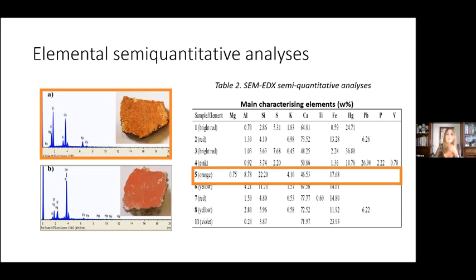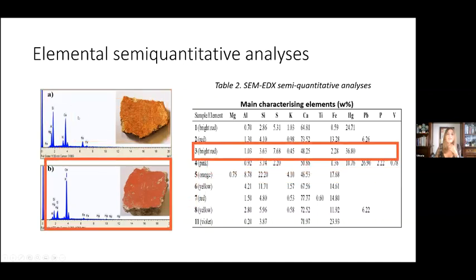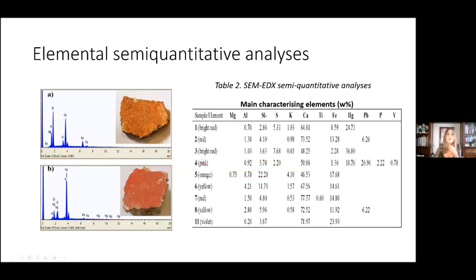The bright red sample three shows instead a significant presence of mercury and sulfur that led to thinking of cinnabar. To summarize, it can be stated that the bright red samples were both mainly characterized by the presence of mercury and sulfur, whereas with the exception of the pink sample, which will be discussed later, in all of the other cases, the main component was iron, found either alone or together with lead,